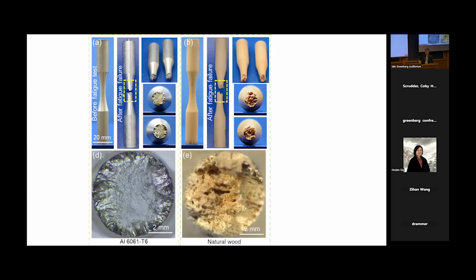We've done this for natural wood as well. So this is a very similar phenomenon, same dimension of the samples, natural wood, and it failed by fatigue, and the fatigue failure is catastrophic as well. It breaks into two parts all of a sudden, and you can see the cross sections over there because this is anisotropic, and then you start to see those wood fibers. So here the wood fiber is along the length direction of the sample.